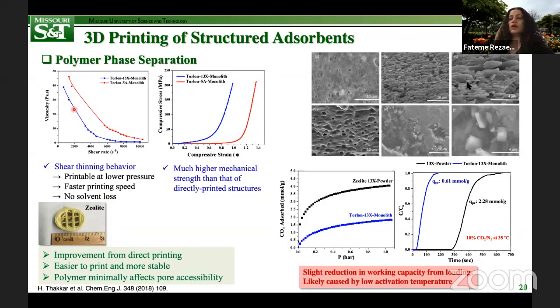And also, increasing the loading will adversely affect the rheological properties of the paste and render it unprintable. This is something that we actually found. In terms of adsorptive performance, we observed a slight reduction in working capacity from loading, which was likely caused by low activation temperature.